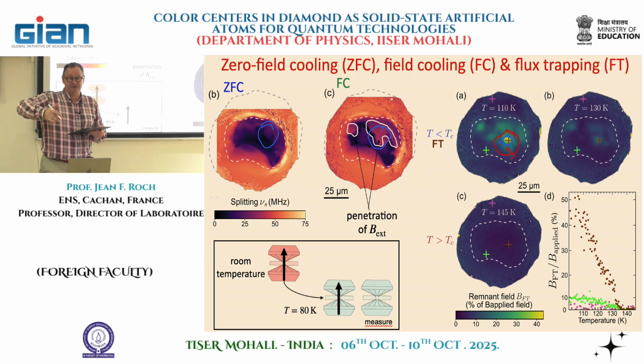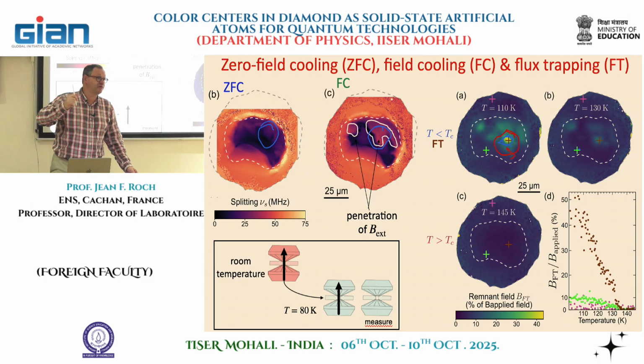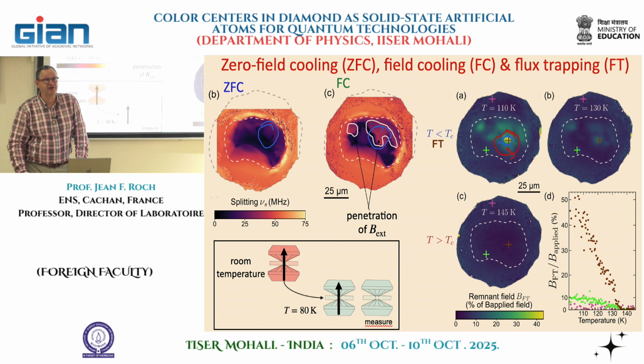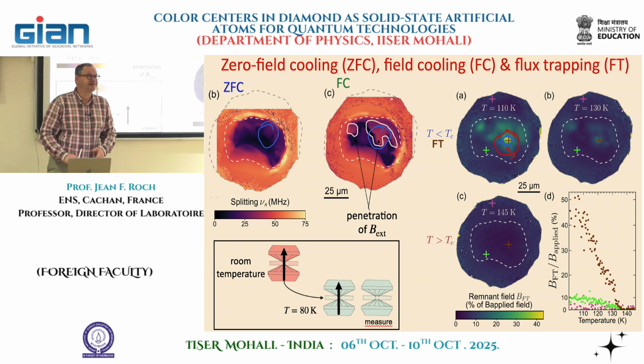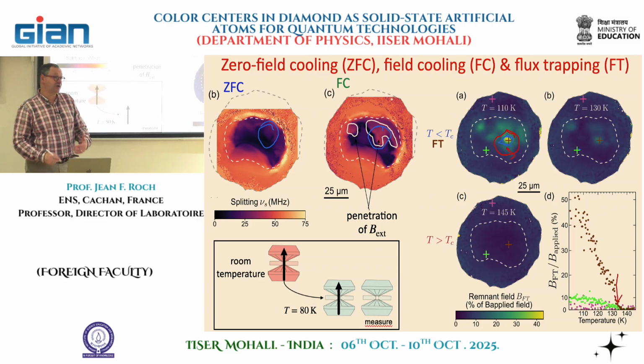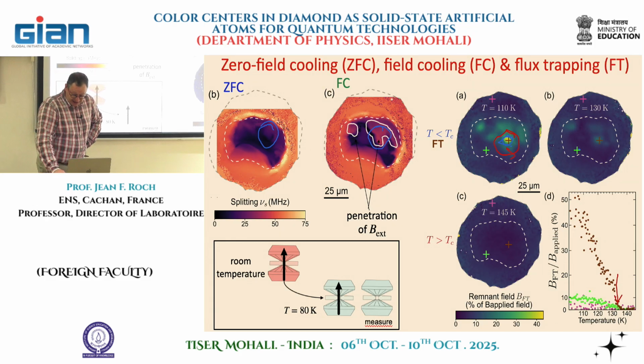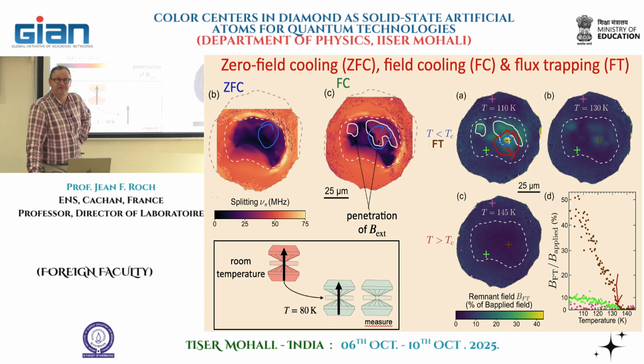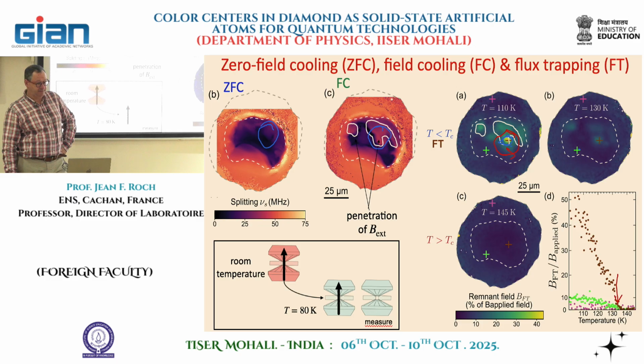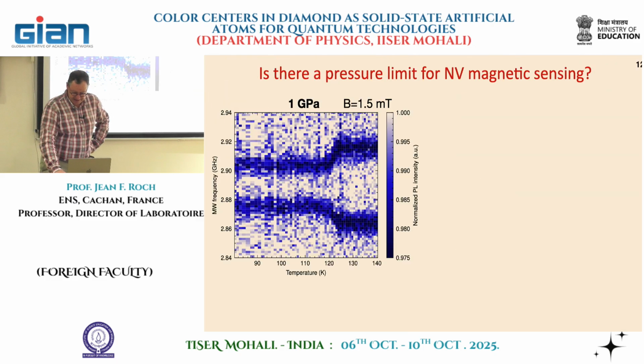And now if we increase the temperature, the superconducting current will decrease progressively, and it will disappear. From this evolution with temperature, we can also determine the critical temperature, in good agreement with the value we obtained before. Okay, and this correlates well. The zone where the magnetic flux is trapped correlates well with the area where we could see a strong difference between the two images we obtained with the zero field cooling and field cooling techniques.